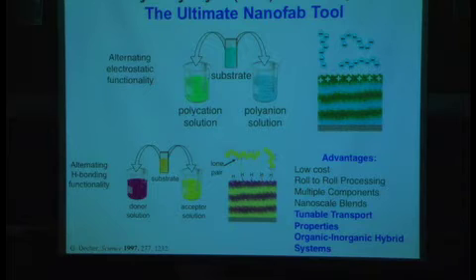That monolayer that's adsorbed has a thickness that is controlled by the pH and the ionic strength. We're actually tuning the conformation of the polymer chain on the substrate from a very flat, tightly stitched, two-dimensional random coil to a very dense and thick, loopy, shielded polyelectrolyte chain, depending on whether we've added salt or tuned the pH to decrease the degree of ionization in weak polyacids or polybases.